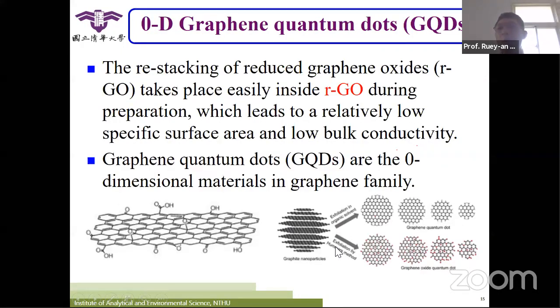So now we talk about some cases here. One is the zero-dimensional graphene quantum dots. We know that the two-dimensional graphene oxides have quite good conductivity, but their optical property is not good enough. So when you narrow down this two-dimensional graphene oxide or reduced graphene oxide, with just several layers, into very, very tiny parts, they become quantum dots. When we talk about quantum dots, it means their particle size will be less than 10 nanometers, best around 5 nanometers. When the particles narrow down to quantum dot behavior, they have quite a unique optical property.